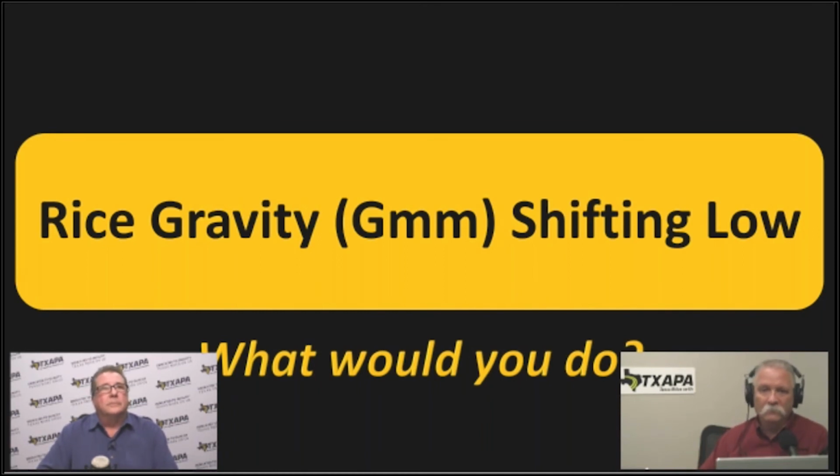First thing we look at is RAP, where we have a GMM problem because we run high RAP and we run a lot of different kinds of RAP. So soft limestones, harder limestones, granite. We've made assumptions, and if that shifts on us, our experience has been we start worrying about that, and we'll grab another one as quick as we can. Okay, and see what's going on.